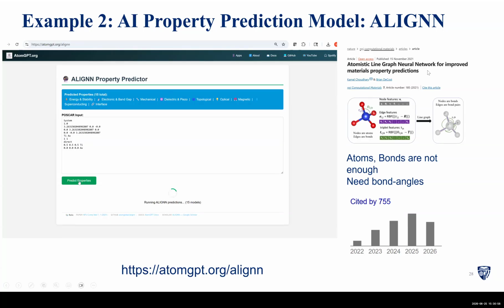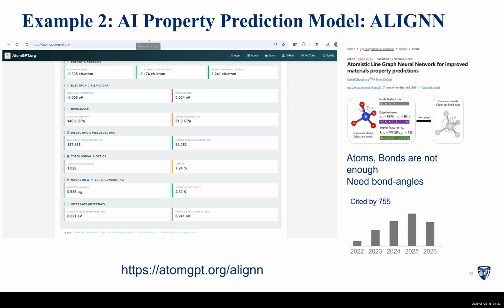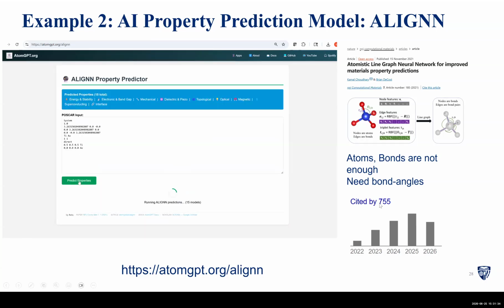So this model, called the atomistic line graph neural network, provided one of the first ways to capture the bond angles using a line graph. And in this way, we can capture angles, dihedrals, and so on. So now we took the JARVIS-DFT dataset and trained models on it. And now if you go to the app and give it an atomic structure, with the lattice parameters as a 3x3 matrix, the element types, and the XYZ coordinates, in just a few seconds it can predict properties such as formation energy, mechanical properties, topological properties, magnetic properties, interface properties, and so on. This paper is cited about 800 times.